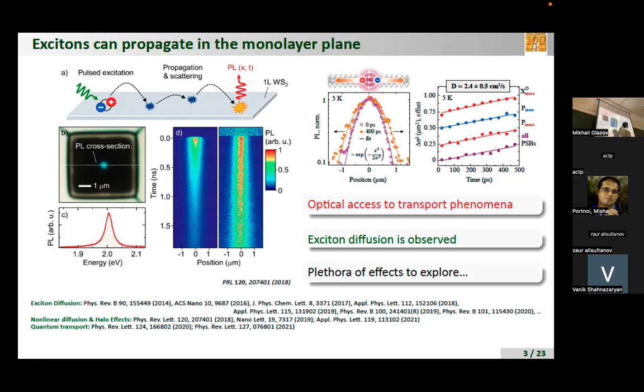Here, the square distance is proportional to the first power of time, meaning that actually the exciton doesn't move along a straight line, but moves along some kind of wiggly trajectory. So it diffuses. My main goal in this transparency was to show that optics indeed provides access to exciton transport phenomena, that one indeed observes exciton diffusion. We will speak about mechanisms of diffusion a bit later.